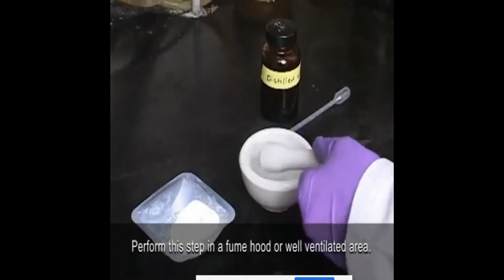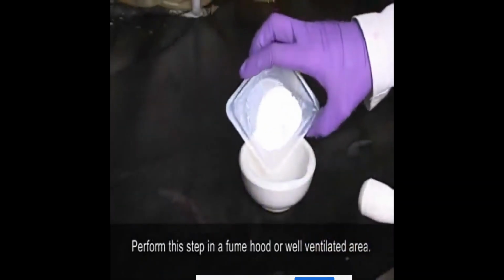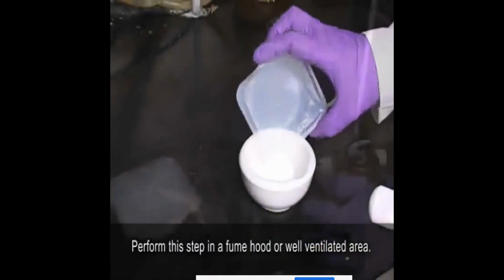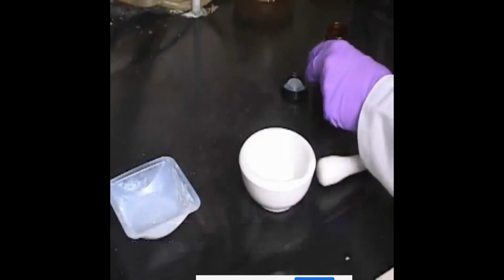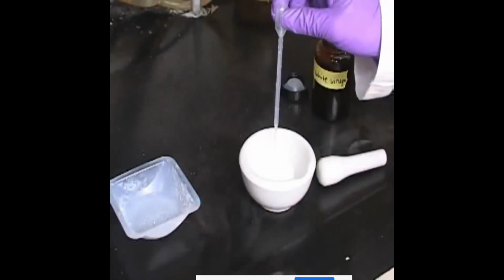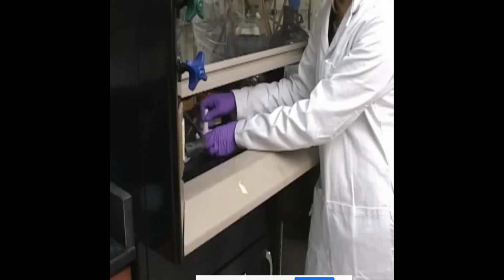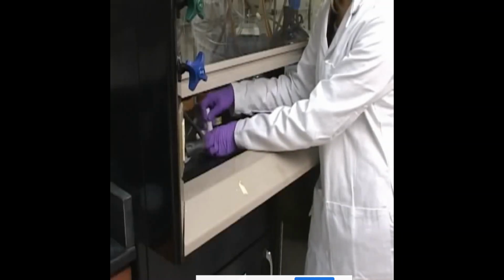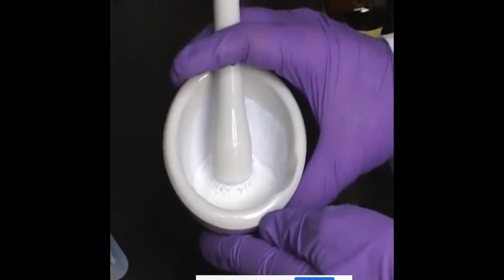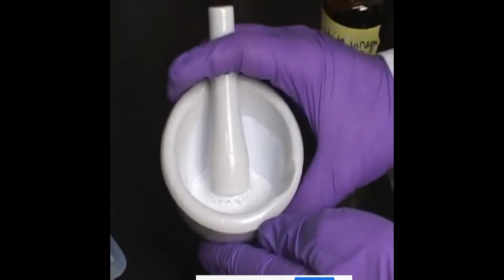Titanium dioxide suspension. Step 1. Start with 6 grams of titanium dioxide powder in a mortar and pestle. Under a ventilated fume hood, slowly add vinegar in 1 milliliter increments to the solution, grinding well each time. The process should take around 30 minutes and will result in a very white, milky, paint-like solution.